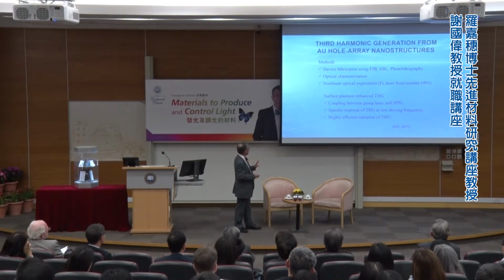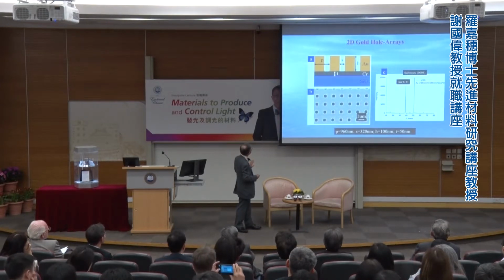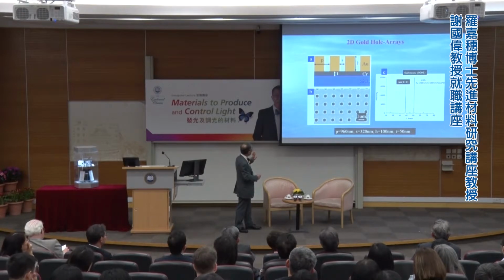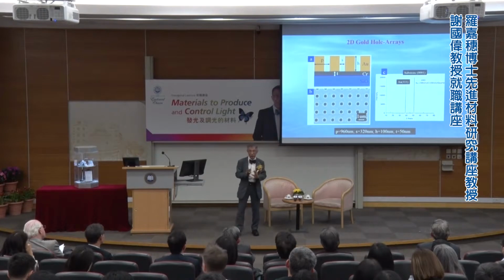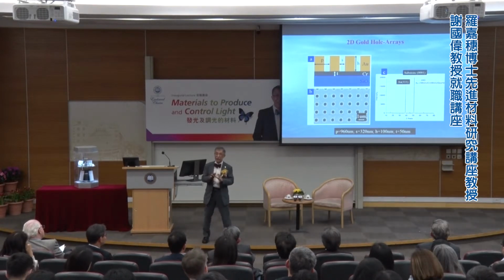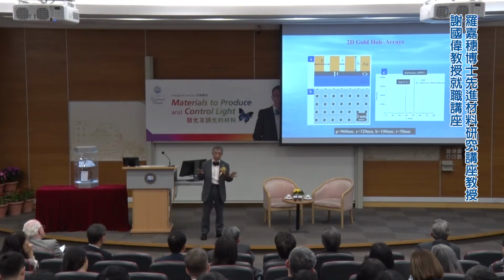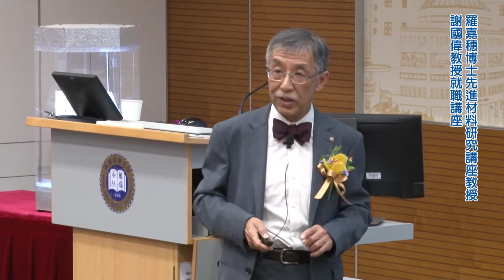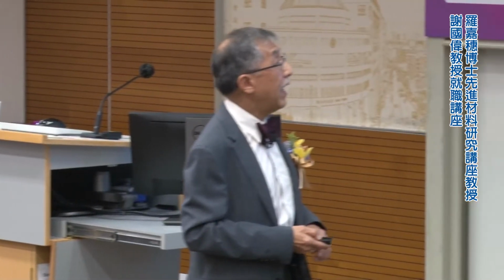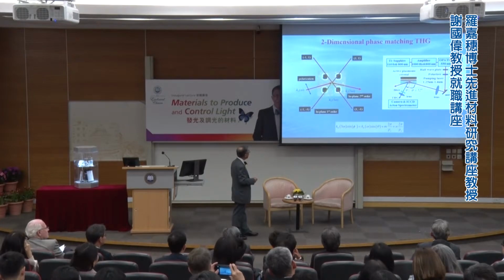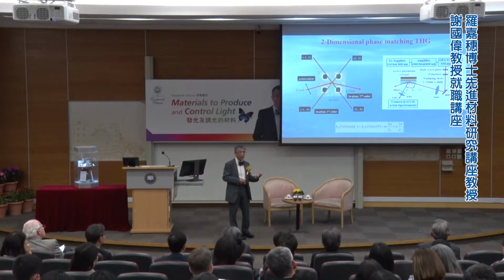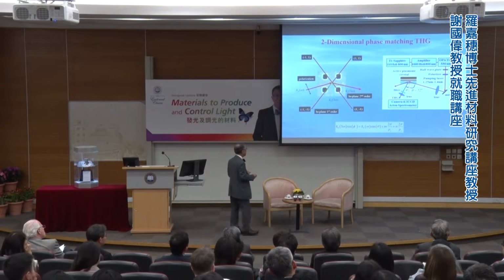So we did some work on it. I will jump a little bit here. What we've done is make a little bit of holes in a gold layer. By doing this, we're creating a two-dimensional gold layer that creates a special property using the free electrons inside gold, what we call plasmonic. In this experiment, we shine the light onto it, and then we collect what we call harmonics. In this case, it's the third harmonic.